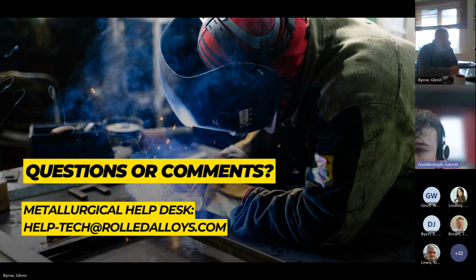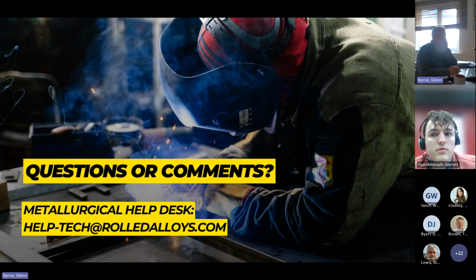Question is from Jeff Warburton. Do you recommend the use of argon-nitrogen gas mixtures? I think the answer to that is yes, we do, and people have used it extensively to basically pass ferric chloride corrosion test requirements on procedure qualification. What I would add is that these days consumables with a minimum PREN of 42 are available, whereas older versions had a minimum PREN of about 40.5, and we find that the PREN 42 consumables tend to be very robust in terms of corrosion resistance on their own, without support of argon and nitrogen shielding gas mixes.